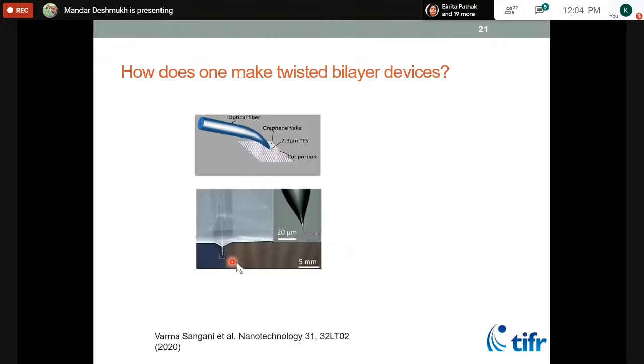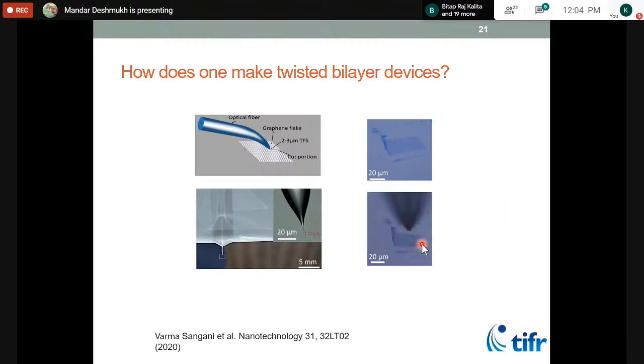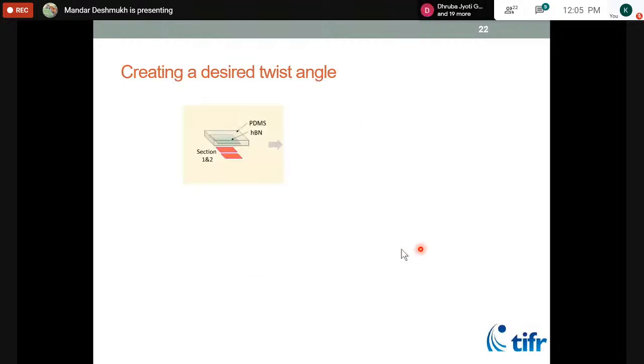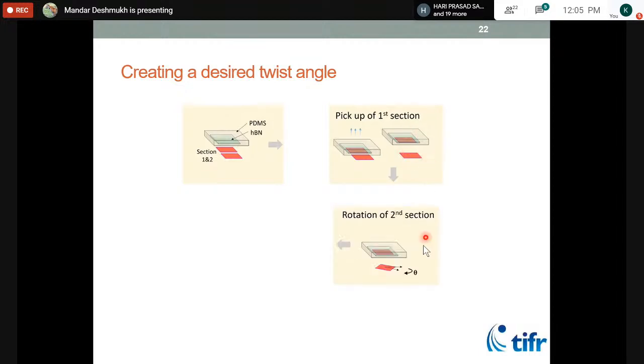And you cut it into two pieces using this very sharp scalpel. So this is one sheet of graphene. You cut it into two pieces. Now, because this graphene was part of the same structure, they are aligned completely. So then you pick up one layer on a piece of rubber. Then one layer goes away, the other cut part remains behind. Then you rotate the lower one by a precise angle that you want, 1 degree, 2 degrees, whatever you want.